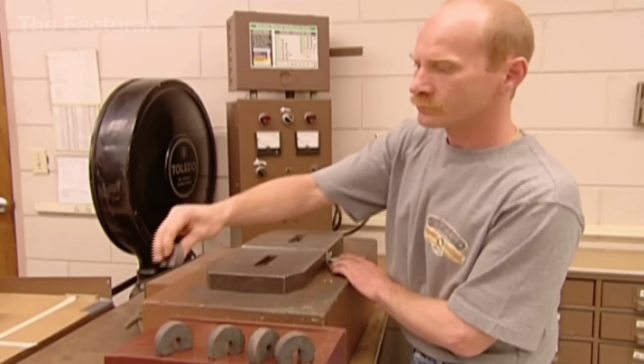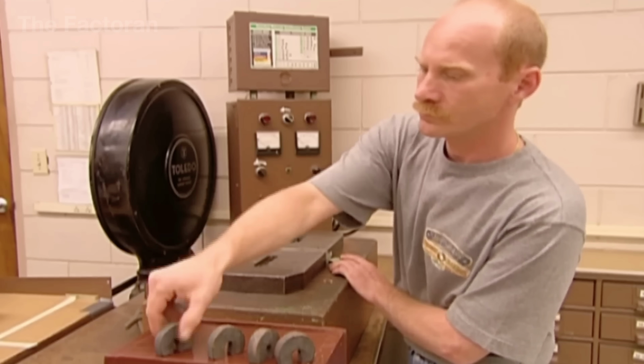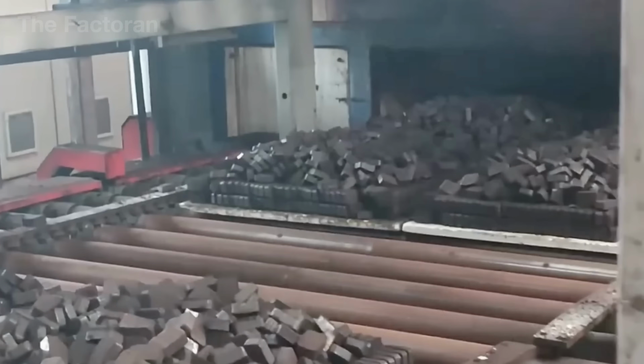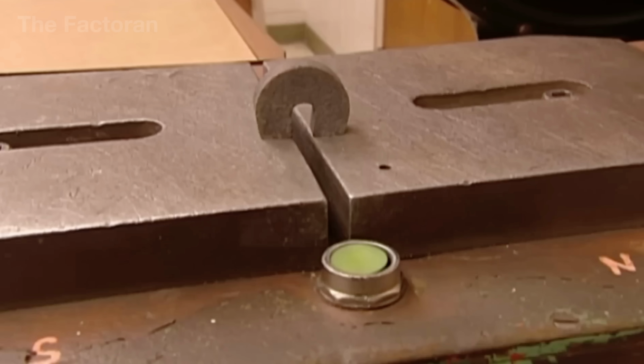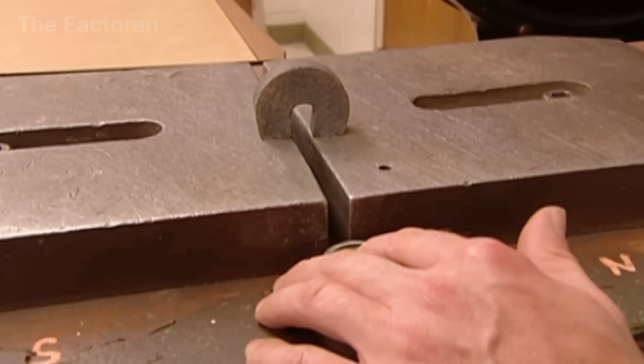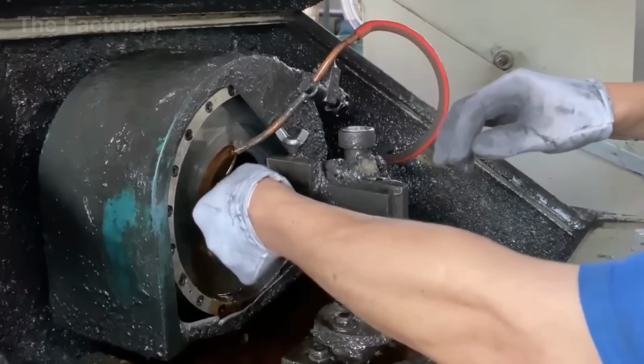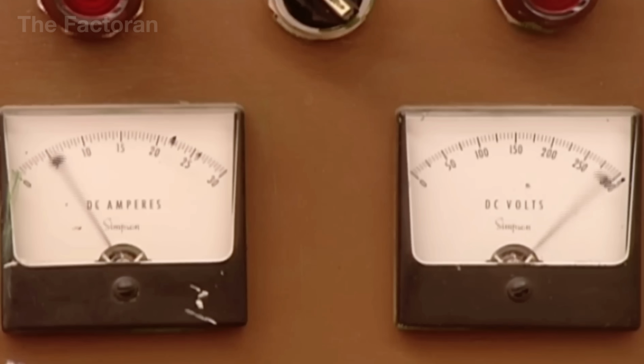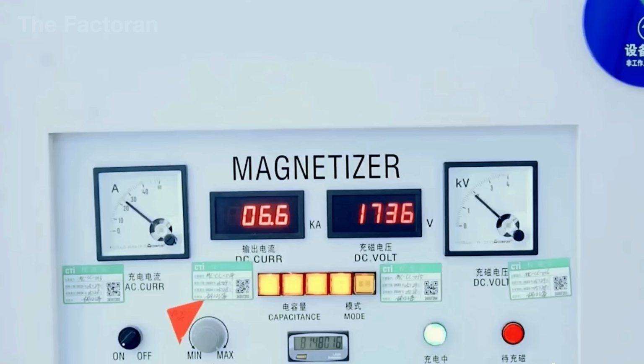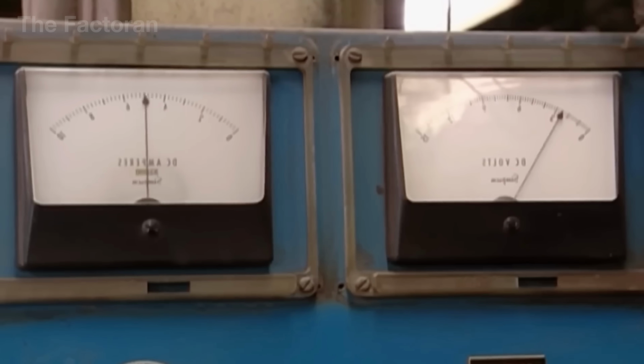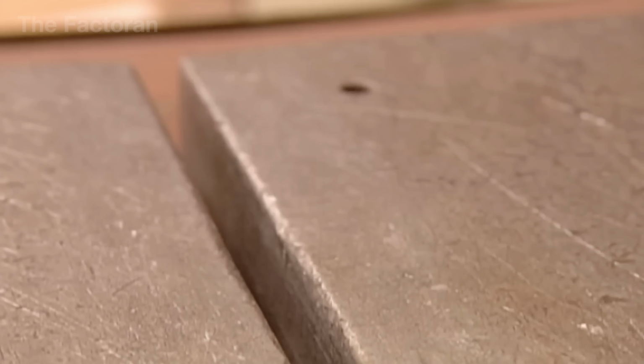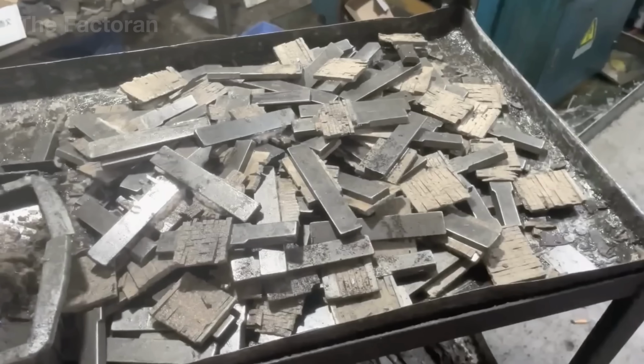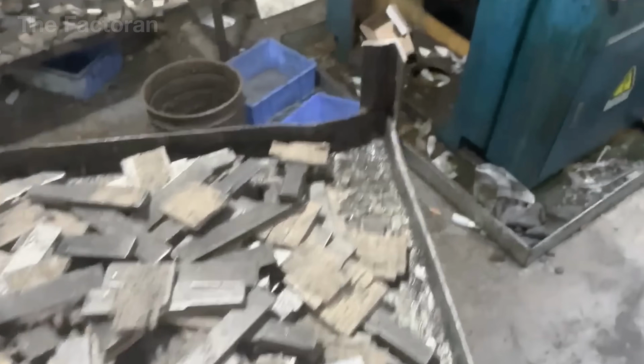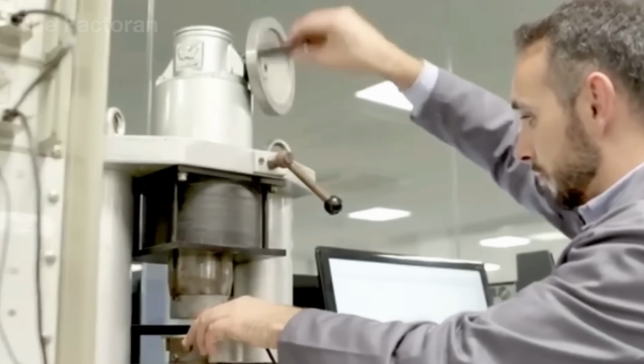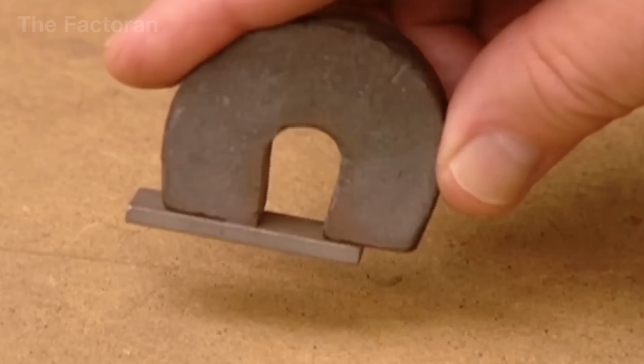If the magnetic pulse is too strong, internal stress can distort the crystal structure. If too weak, some domains remain disordered, causing a noticeable drop in magnetic strength. After magnetization, each magnet's surface field is measured using a Hall sensor, and its polarity is verified through an automatic orientation tester. Those that fail to meet specifications are demagnetized and reprocessed, while the qualified ones are sealed and prepared for the final inspection and packaging stages.